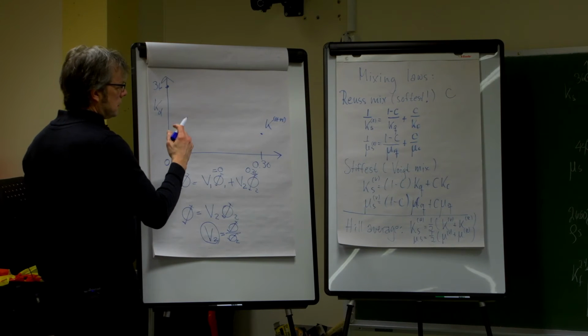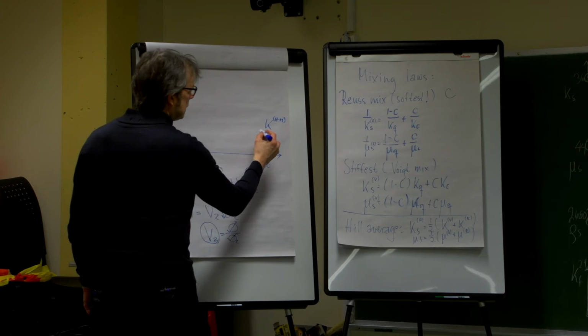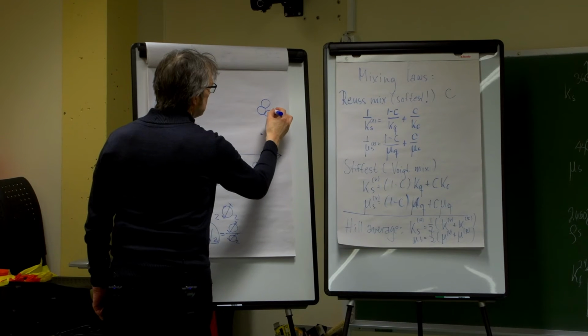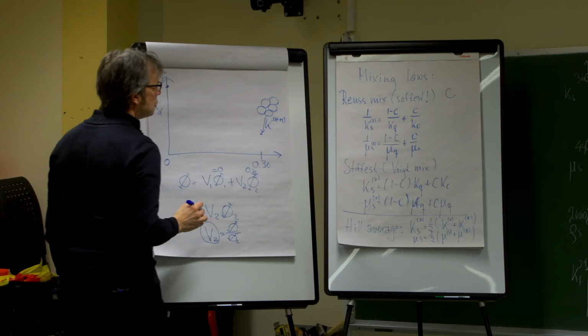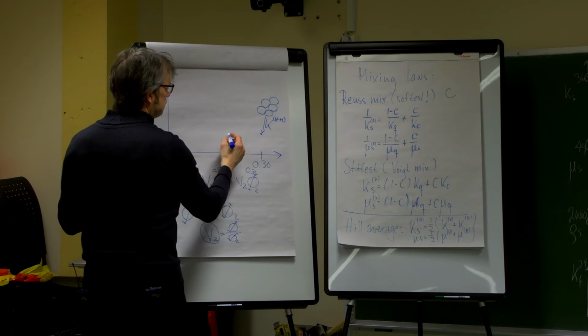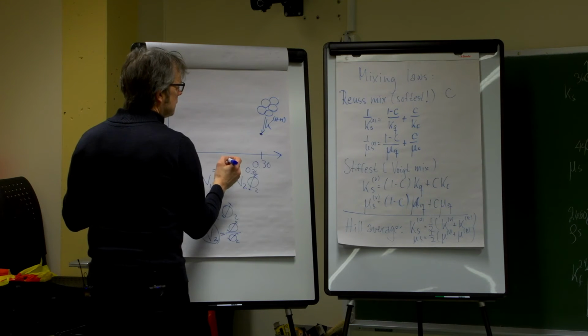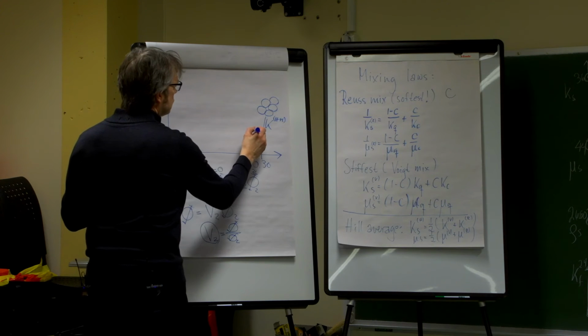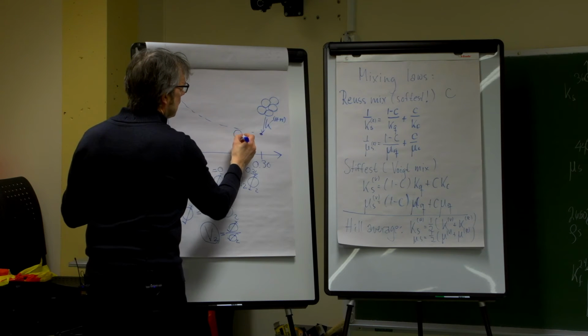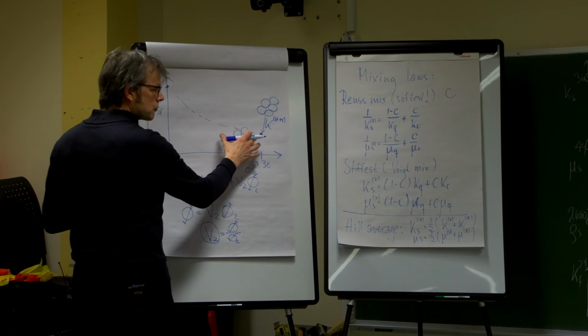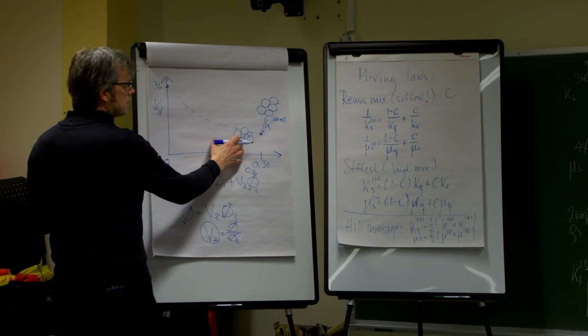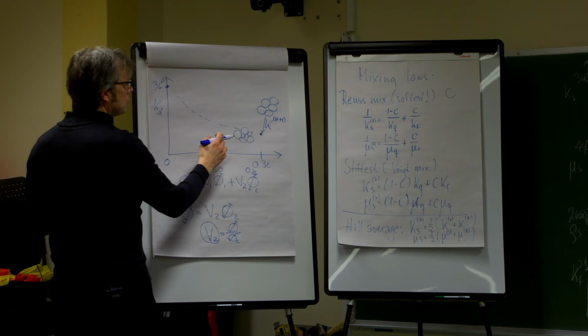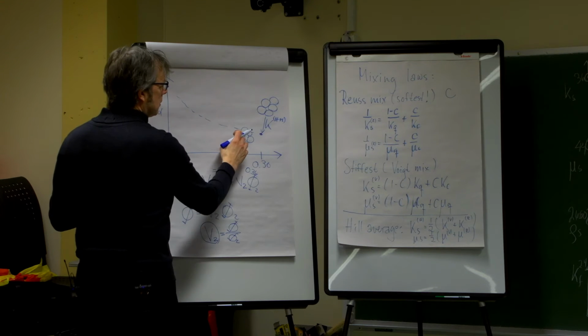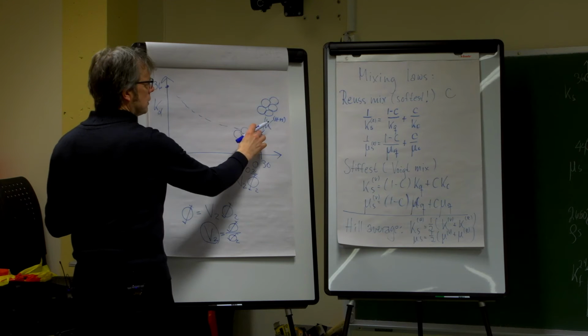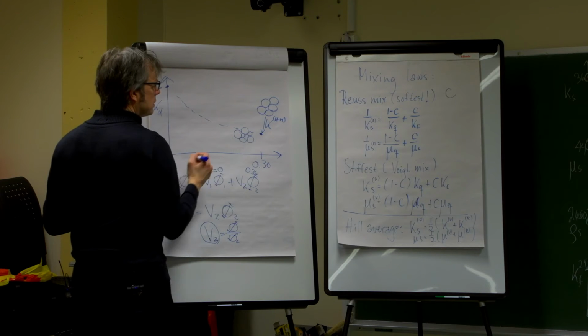So then I could use, as I said, any mixing model, but in here we assume that, okay, we have a perfectly sorted medium here. That's the interpretation of the Hertz-Mindlin point. If I use the Hashin-Shtrikman lower bound, and this is unconsolidated, I could try to interpolate somewhere in between here, saying that, okay, I end up with less well-sorted material. And if you see the cartoon of the rock for the lower Hashin-Shtrikman bound, it's a kind of mixed size property. In this case we just have quartz, so of course we mix a large grain here with a set of smaller grains here. So that's the interpretation here.